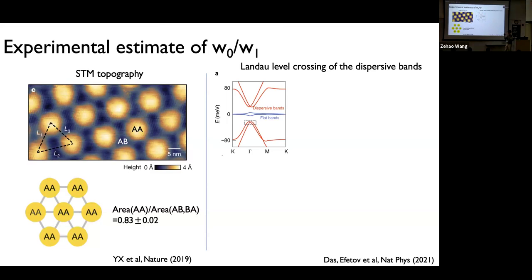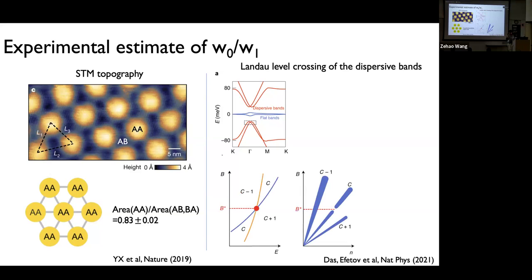And actually, that level of splitting is determined by this W0 over W1. You can check out the paper if you are interested. And the point is that if you now look at the Landau level of the dispersive band, what you will find is that the Landau level has to cross, because you kind of have two bands, right? And then the two bands already cross, and then if you were to compute the Landau level spectrum, it would look very, very different.